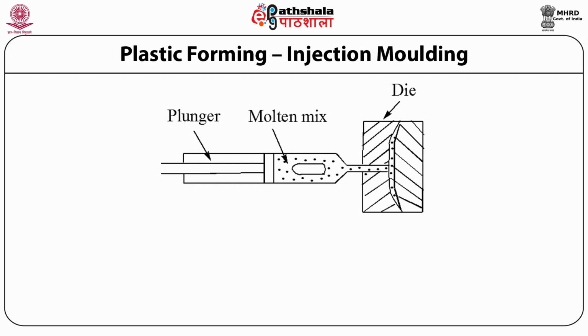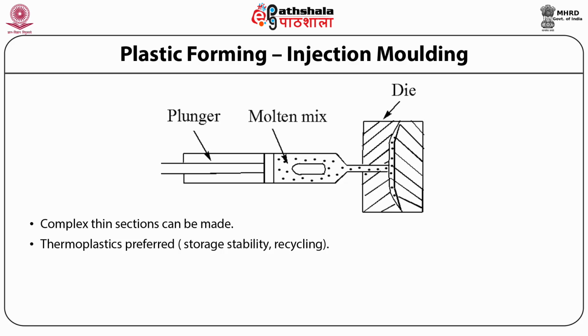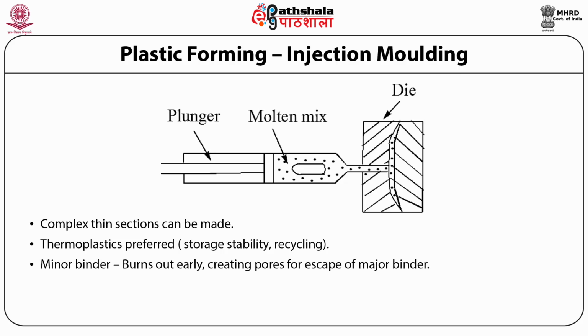Now the next is injection molding, which is a type of plastic forming. As mentioned earlier, in injection molding, a molten thermoplastic heavily doped with ceramic powder is injected into a die as shown in this figure. It is a rapid process and can produce complex shapes with thin sections. In injection molding, thermoplastics are preferred over thermosets because of factors such as storage stability and reusability of the scrap. Two types of thermoplastics are generally used. One is called the minor binder, which during the post-forming removal of the polymer burns out earlier and provides pore channels for the escape of the major binder, which burns out later.